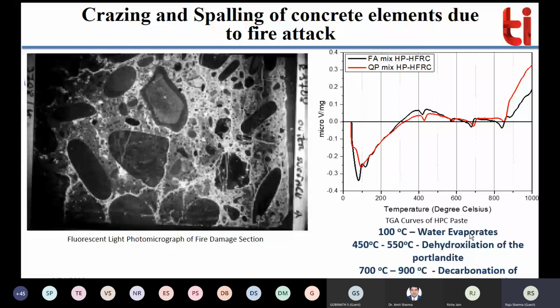So when your concrete is subjected to fire up to 100 degrees Celsius, the initial water in the gel phase, in the micropores, in the pore voids, in the capillary voids, whatever water is there, started to evaporate because of the heat. But once the temperature goes beyond that point and reaches around 400 to 500 degrees Celsius, your calcium hydroxide may start to degrade, and then cavities may form. Because of that, your bonding may decrease and spalling may happen. And then if the temperature keeps increasing, you will see that the main favorable compound of the concrete, calcium silicate hydrate, will start to diminish, will start to be consumed by the fire.